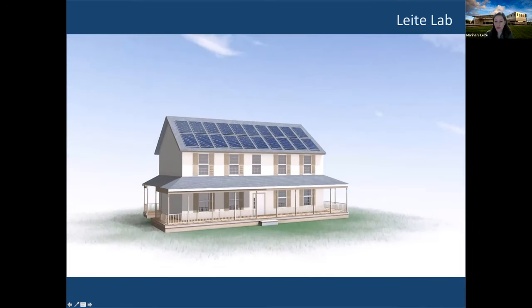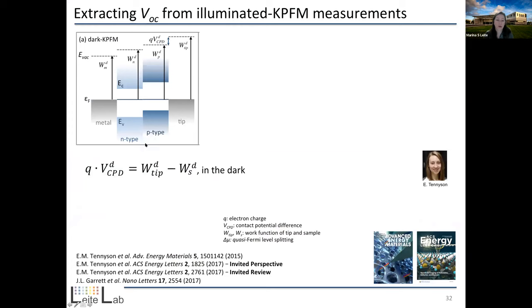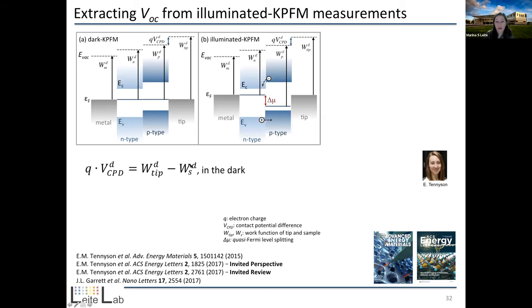and design better materials. So basically, the work that Elizabeth and Joe Garrett did back in their grad school was the following. We basically came up with a way of mapping locally the open circuit voltage, and I'm running out of time, so we'll go a little bit fast on that. Kelvin probe force microscopy essentially measures the difference in work function between a conductive tip and the surface of a sample. So what we did that was different, I would say, is that we decided to do these measurements not only under illumination, but actually grounded the tip with respect to the metal contact that we have in our device.